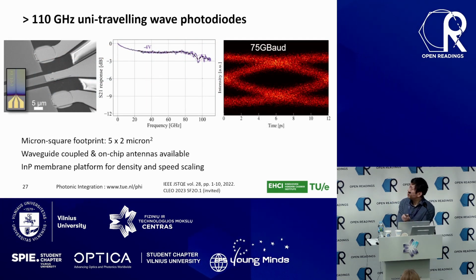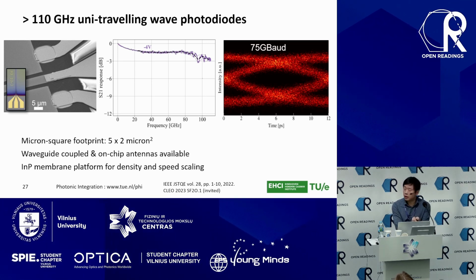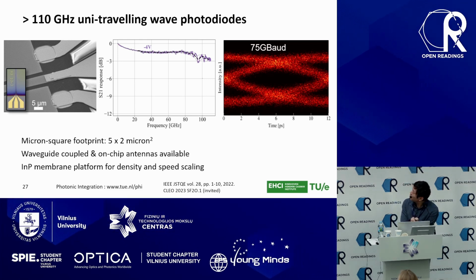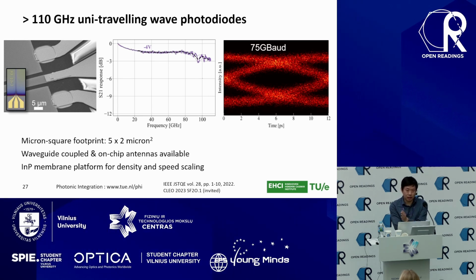So we created such a photodiode using our technique. On the left side, you see the image of the photodiode, and according to our measurement, it can really operate very fast. At 4 volts bias, we can achieve an electro-optic bandwidth beyond 110 gigahertz. Actually, our latest design can go even slightly better, towards 150-ish gigahertz. So you can already connect optical band to millimeter wave band. And another thing is that such a diode is extremely small, even though it's very efficient. It's only 5 by 2 square micrometers.